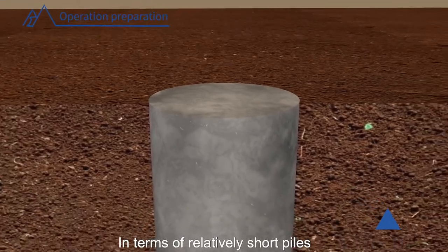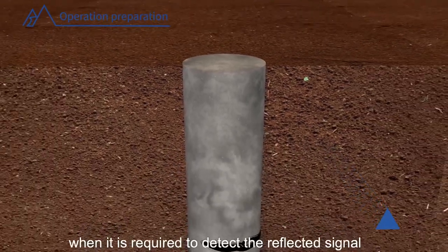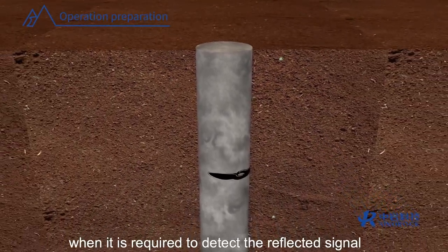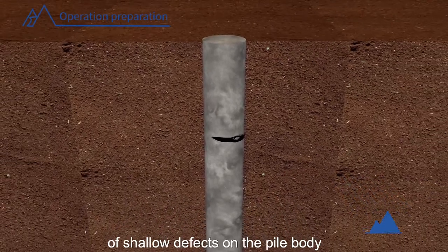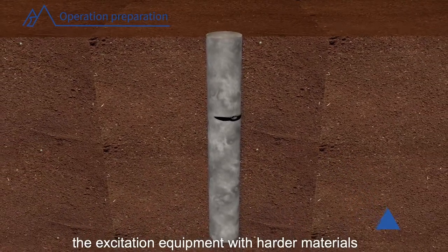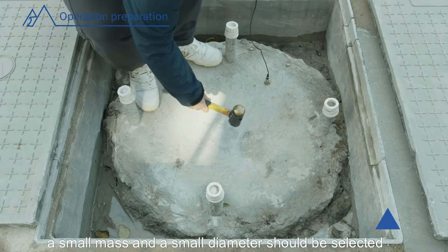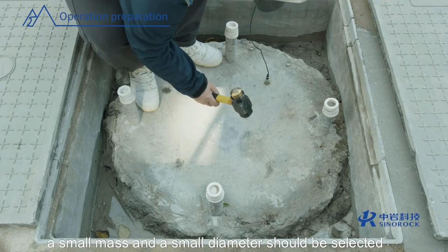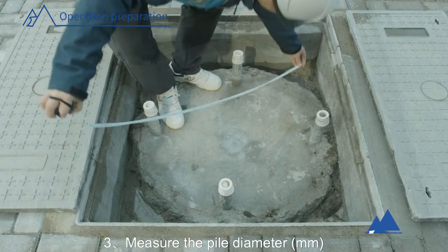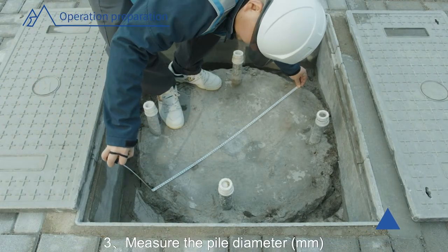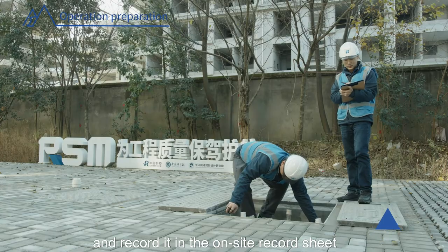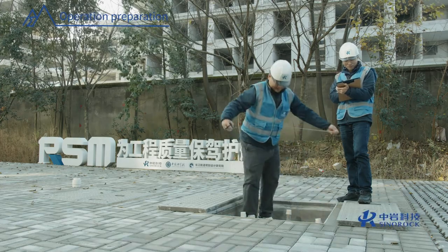In terms of relatively short piles, when it is required to detect the reflected signal of shallow defects on the pile body, the excitation equipment with harder materials, a small mass, and a small diameter should be selected. 3. Measure the pile diameter in millimeters, and record it in the on-site record sheet.